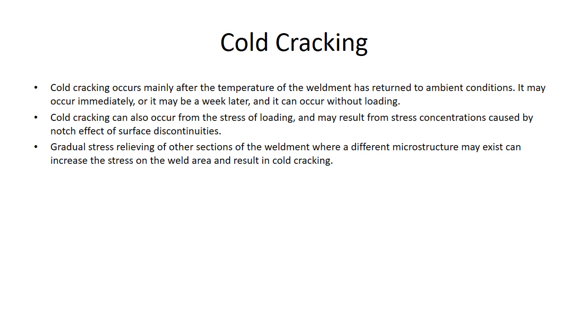Cold cracking occurs mainly after the temperature of the weldment has returned to ambient conditions. It may occur immediately or it may be a week later, and can occur without loading. Cold cracking can also result from stress concentrations caused by notch effects of surface discontinuities. Gradual stress relieving of other sections of the weldment where a different microstructure may exist can increase the stress on the weld area and result in cold cracking.